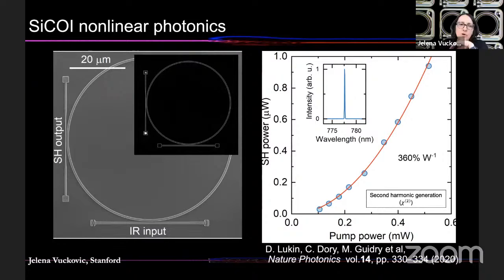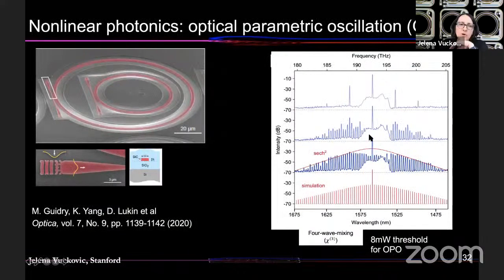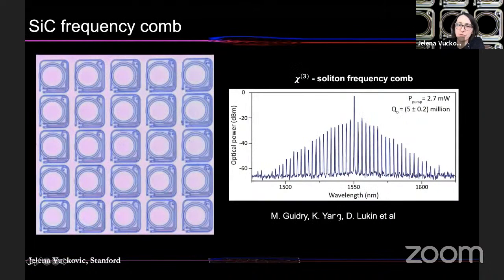So now we actually should be able to measure this with much higher efficiency because it scales as Q factors squared. And also, very recently, we demonstrated optical parametric oscillation with low thresholds, or 8 milliwatt thresholds, and then at higher pump powers, you see microcombs. So this is, again, employing optical nonlinearity in silicon carbide, so you can actually even scale this up to stable soliton frequency combs. So this is a very recent measurement from a few weeks ago that we made, and we can demonstrate soliton. This is a stable soliton frequency comb on a silicon carbide chip with very low threshold. And of course, this is due to strong nonlinearity and also high quality of the structure that we demonstrate.